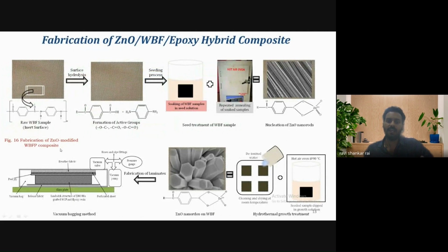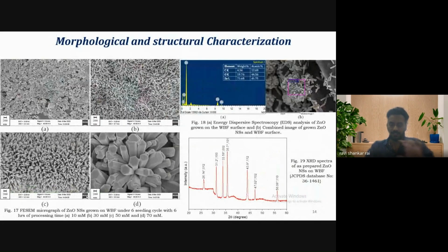So this is the entire layout of the fabrication of the ZnO woven basalt fiber epoxy hybrid composite. It started with surface hydrolysis, seeding, then growth treatment, and after that, 5 sets of these samples were kept in a layer-by-layer structure, and we infused the polymer matrix with the help of a vacuum pump. The entire system is like a vacuum bagging method. After 36 or 48 hours of curing time, the entire sample has solidified into a BFRP panel.